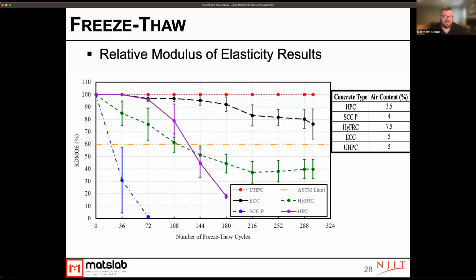And that may have to do with the certain type of systems that are in there, and the different fibers that are in there causing more expansion during that freeze-thaw, maybe allowing water to get into places that doesn't have access to the air entrainment. So more research really needs to be done to understand why that HyFRC system performed that way. But we do see that the ECC and UHPC, both with moderate levels of air entrainment, only 5%, both